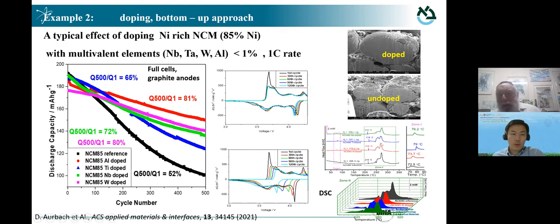When we use DSC, differential scanning calorimetry, we see that whenever we have electrochemical stability, the interaction between the electrolyte solution and the active mass at elevated temperature is lower. We have less heat evolution, and the onset temperature are higher. And most important, after cycling, we see that the doped material, where we have stable behavior, is well integrated.